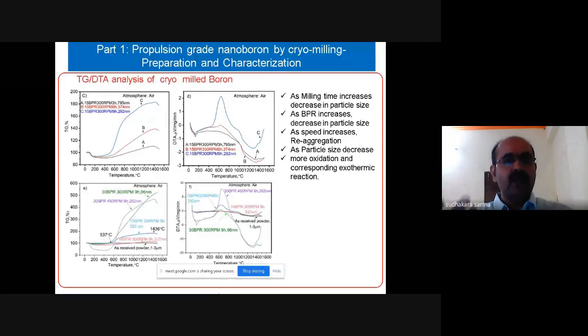For that, we have done TG-DTA analysis, thermogravimetry and differential thermal analysis. It is a graph of temperature versus thermogravimetry, that means percentage mass gain. With heating, there will be a mass gain. Why the mass gain? I will explain. You can see here the three curves.